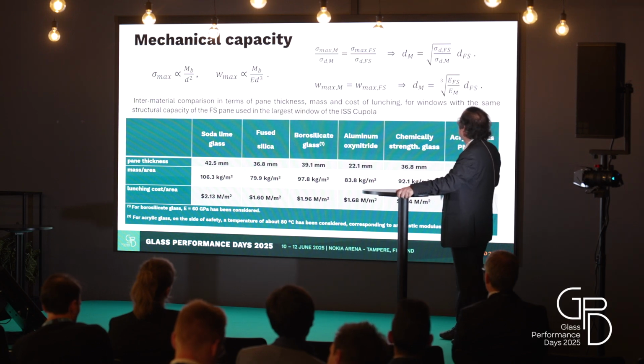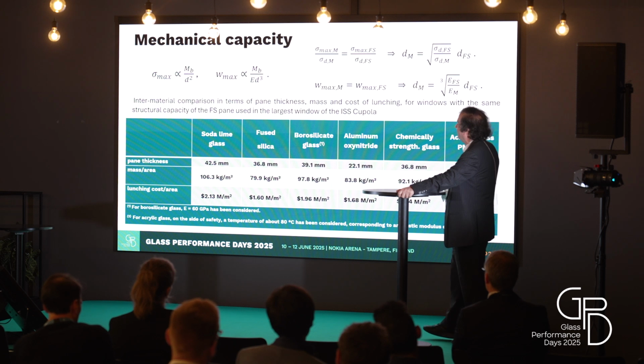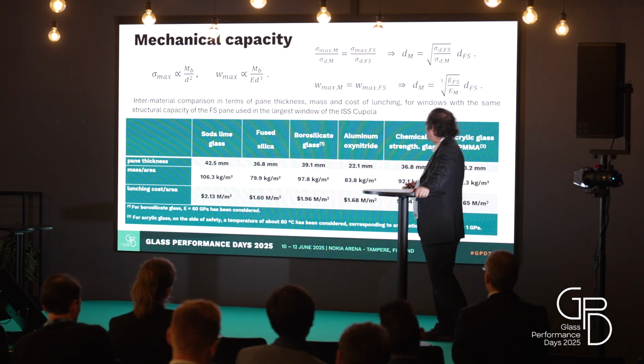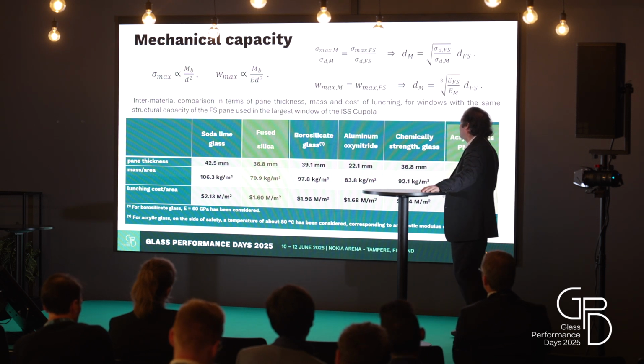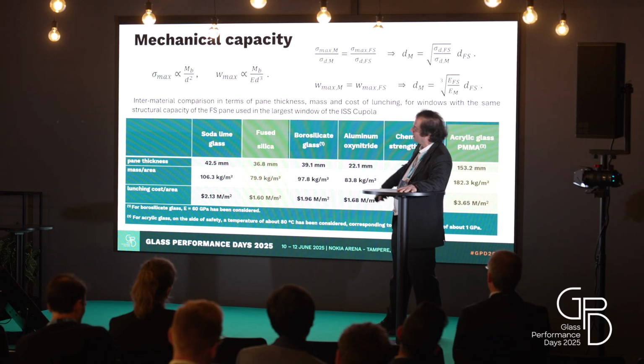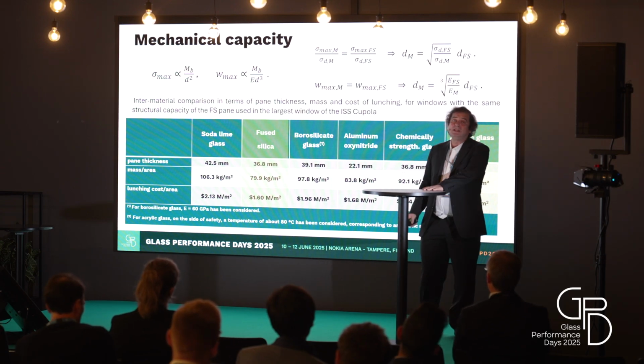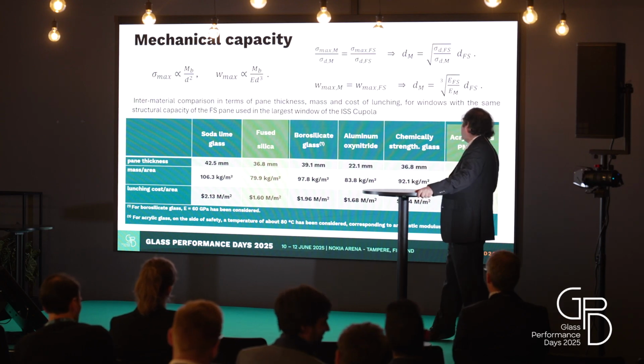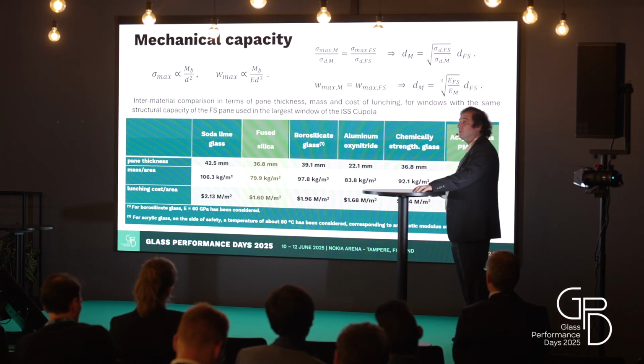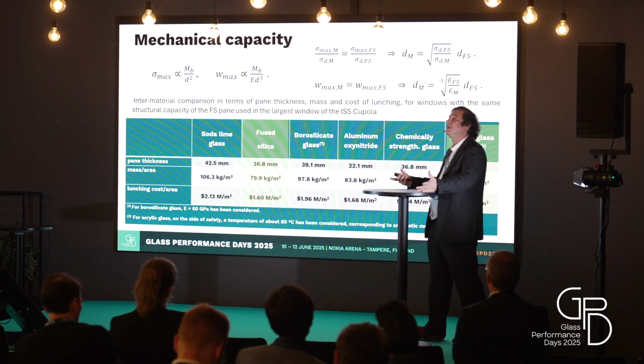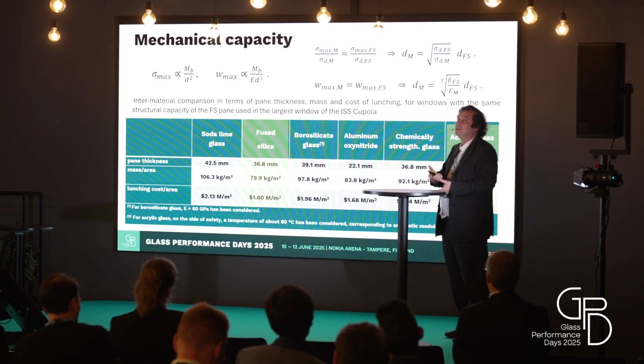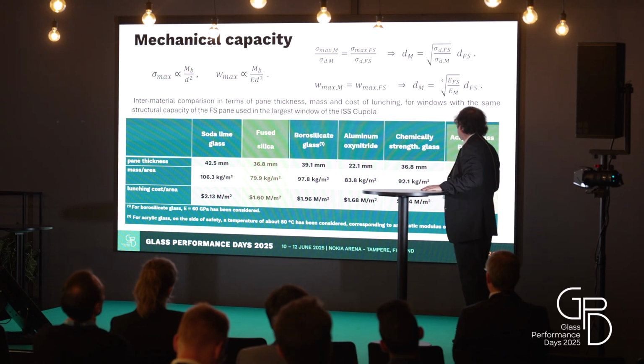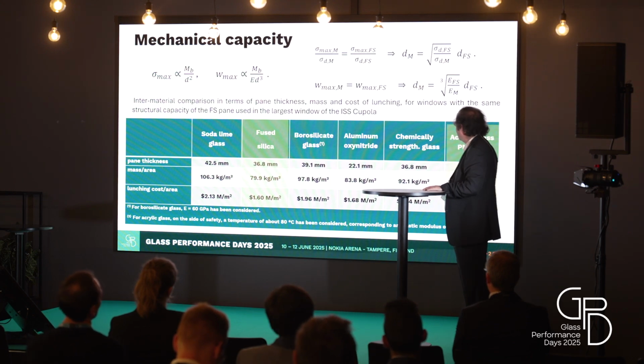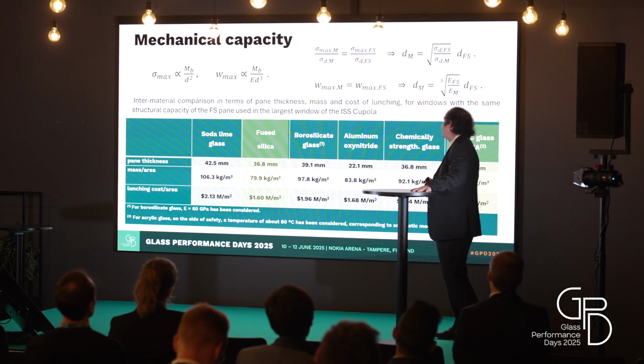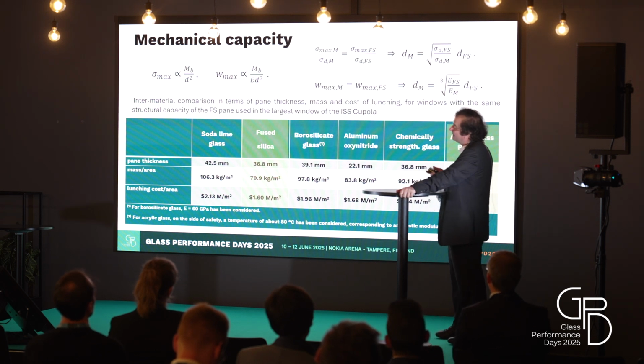For example, if you consider the pane that has been used for the International Space Station, you can see that the launching cost is about $1.6 million per square meter. If you use acrylic glass, it is true that the weight is less, but if you want to make a large window, you have to increase the thickness to have the same stiffness. And so the price is about double that of a fused silica pane. So you have to be a little bit careful about that.